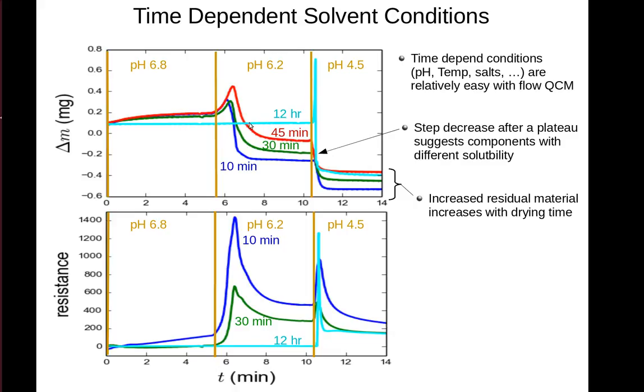However, if the film is dried for 12 hours, there is minimal swelling at a pH of 6.8 or 6.2. However, when the pH is shifted, step change to 4.5, there's still the very rapid swelling and release as needed. Again, the resistance shows very similar information here.